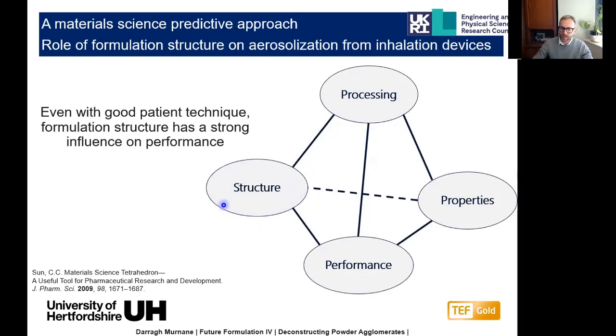And even with good patient technique, the influence of the powder microstructure is massive on performance. And this is the one area that we've really struggled to predict, the area that we struggle to understand, and the area that we struggle to measure for really 20 to 30 years in dry powder inhalers. And this is the big barrier to trying to understand the reproducibility of performance.